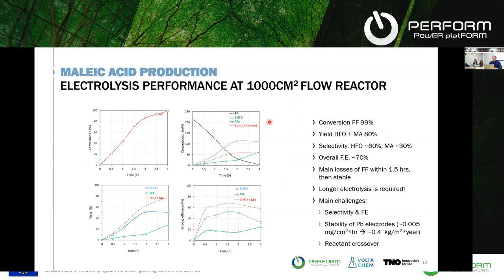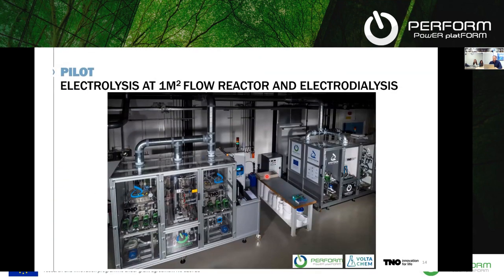Well, now with these results in hand, we are really ready to scale up even further to the full pilot setup. With this 1,000 square centimeter cell, we can reach about 50 grams per hour of product, but that's not sufficient to cover our target. So then we turn to this pilot setup, again realized by EasyTech, that has about a square meter of reactor flow surface area with all the balance of plant around it.